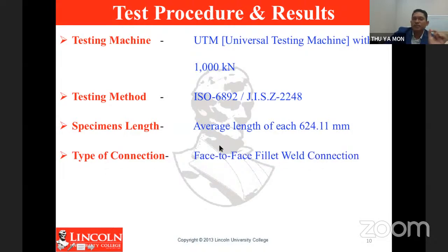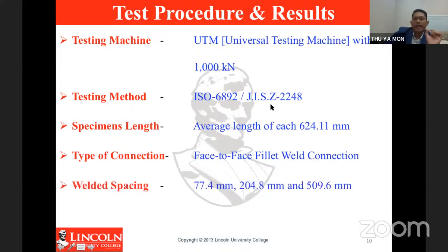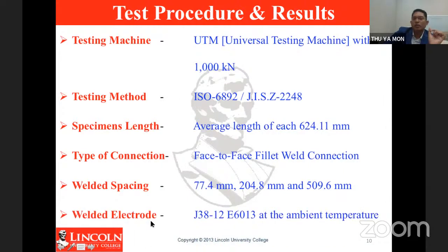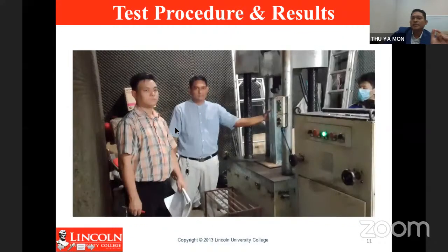The specimens are welded using arc welding, and they are joined with a face-to-face fillet weld connection. The weld spacing, which I have already mentioned before, ranges from 77.4 millimeter to 509.6 millimeter. The welding electrode used is J3812 E6013 at room temperature. This is the evidence photo of the experiment that I did in November 2021.